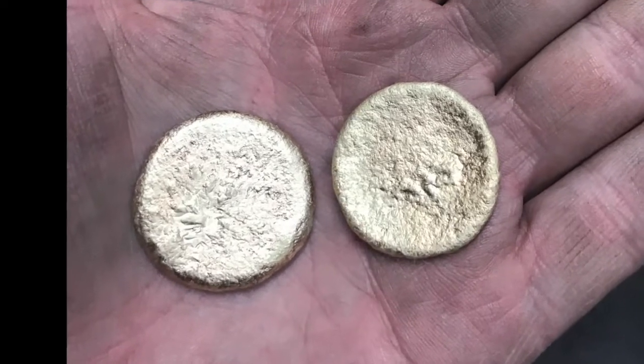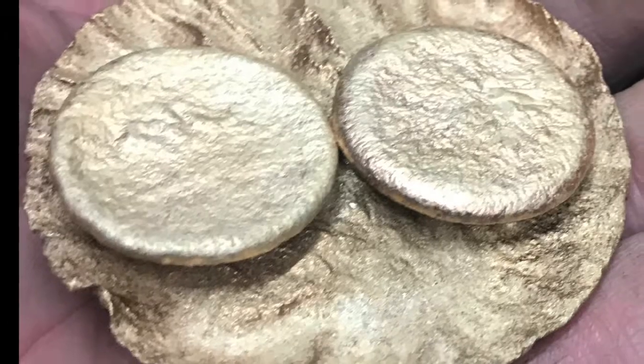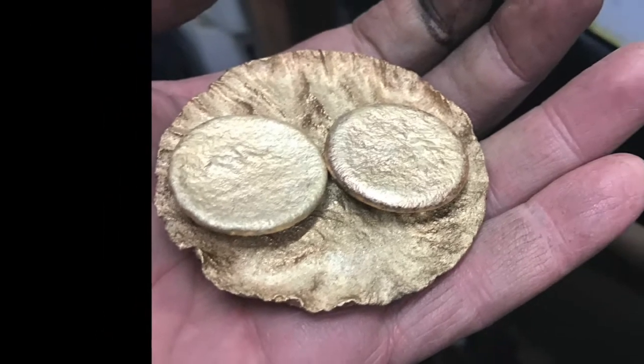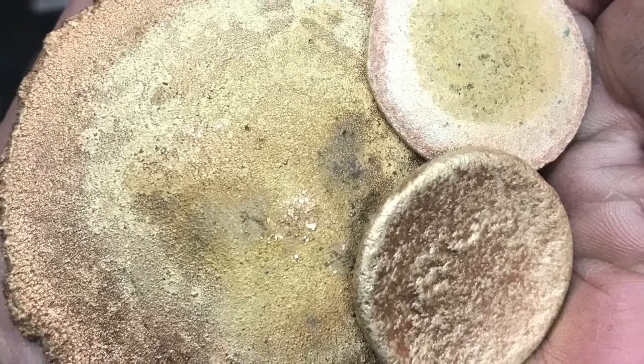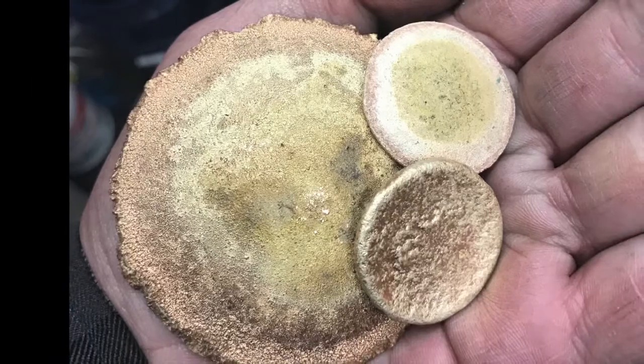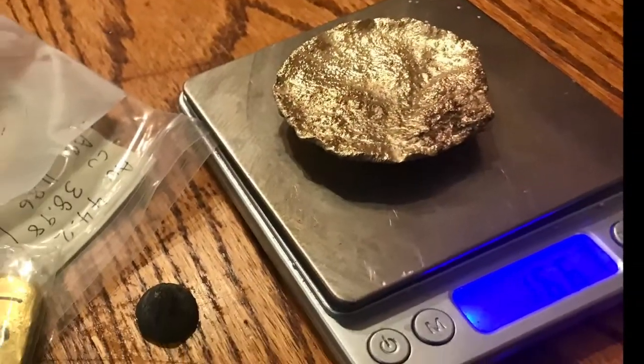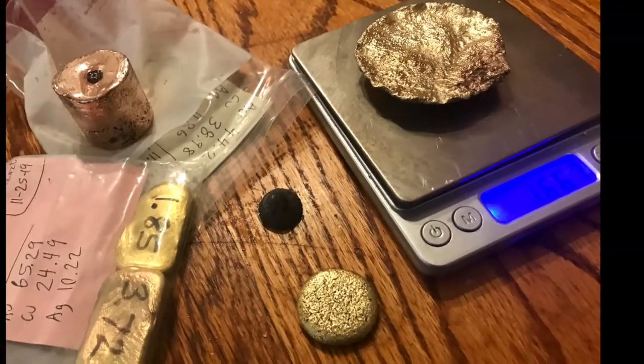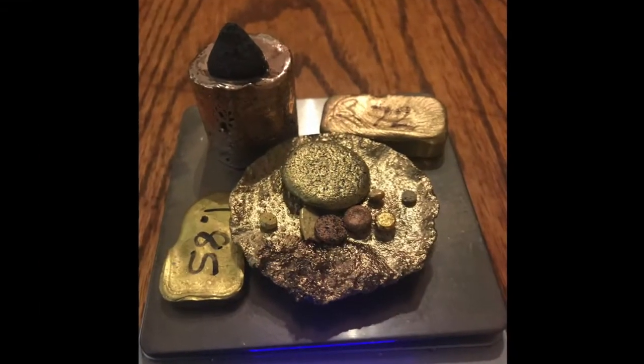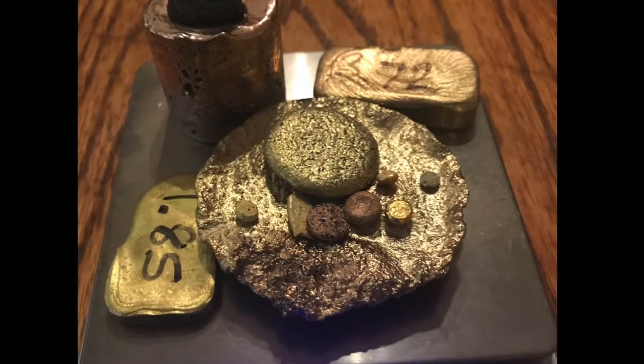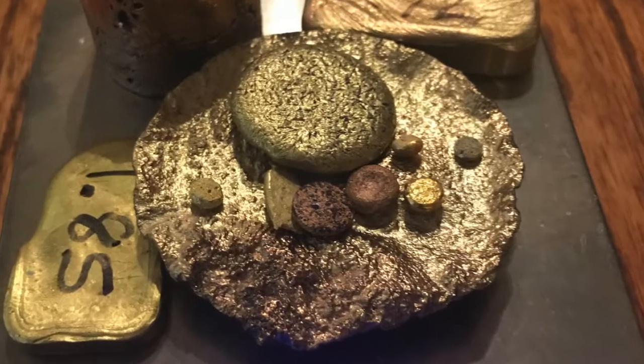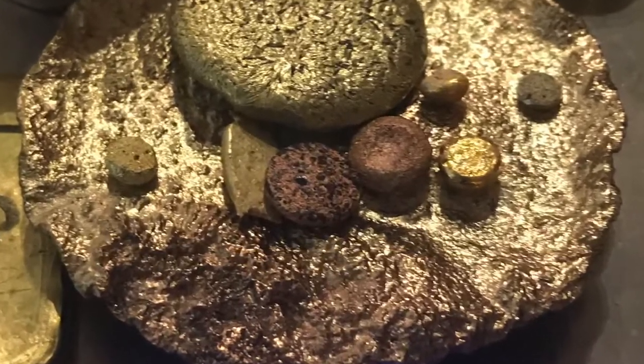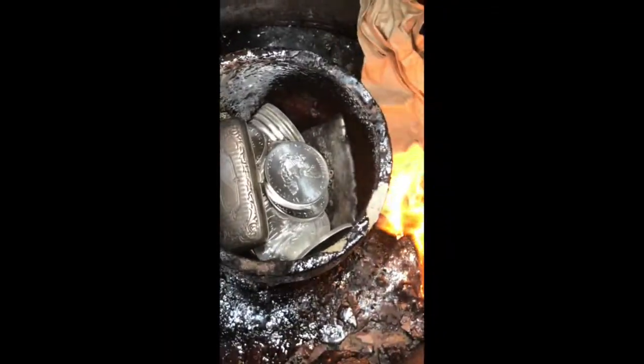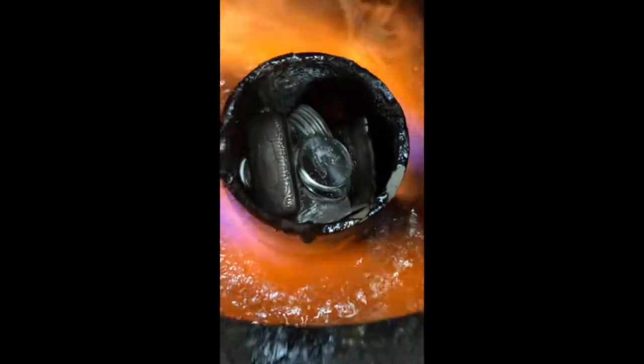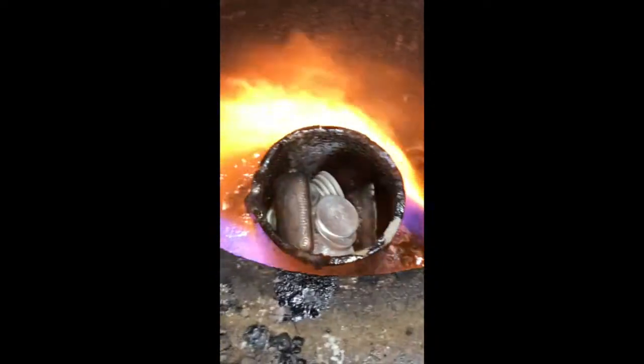As you can see in a picture coming up, there were quite a few different pieces of varying purities that needed to be added all together. Some had more copper than others, some had more gold than others. There's a good example right there. That was melted all together with a specific amount of silver to get to a certain ratio, so that the impurities could be removed with a nitric acid leach.